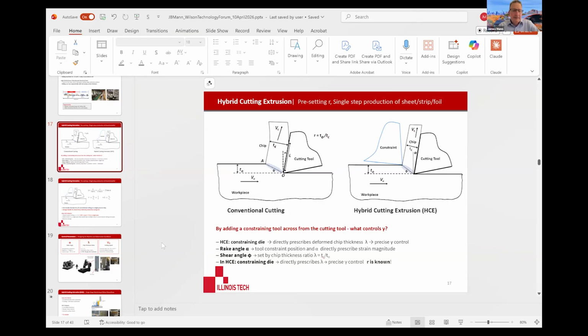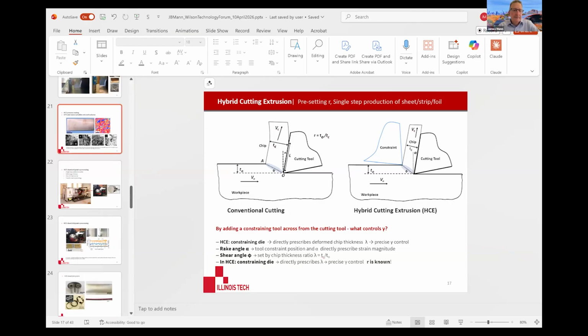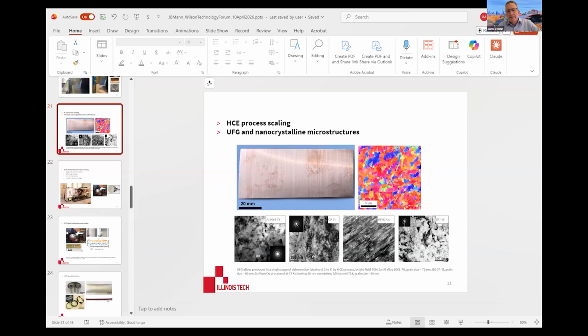But you asked about the consistency of, for example, the microstructure. I'm just going to use this as an example. This is showing the EBSD in this case of the copper. I could produce this copper strip over and over again, and it would have the same texture, the same microstructural texture, same size, same structure. If I change the speed of the process, that might change the actual grain structure.